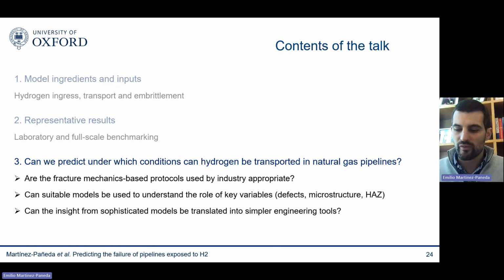So, okay, we have seen that the model is based on physical parameters that are very well understood, that can be nicely and precisely measured in our labs, that have a clear physical meaning, that are known beforehand, so there's no calibration and uncertainty. And we've seen that this model is able to deliver a very good agreement with experiments across a wide range of materials, boundary value problems, fracture, fatigue, lab scale, full scale. So now the question is, okay, we have these models that we trust. What can we learn about those models when it comes to transporting hydrogen in natural gas pipelines?